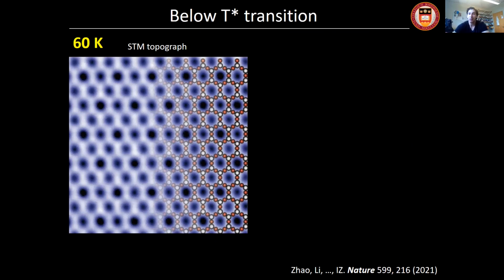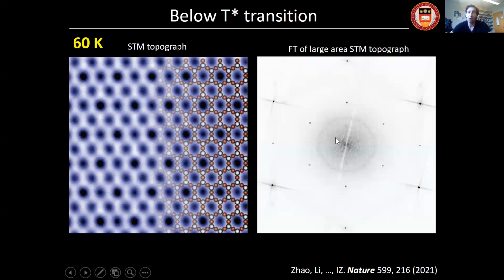So I'm going to start our temperature-dependent STM measurements at 60 Kelvin. 60 to 70 Kelvin is probably as high as we can reasonably achieve with our STMs. And then what I'll show here is the STM topography. You can see this vanadium antimony ball model superimposed on top. And if you Fourier transform this topograph on the left, this is what you get.